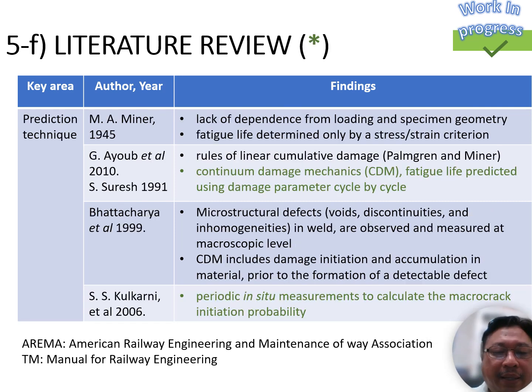On the prediction techniques, the author has extended an additional review on prediction. As per analysis, it shall not lack dependence on loading and specimen geometry. It is suggested by Miner in his literature in 1945, and Ayoub et al. 2010 and Suresh 1991 agree on the application of the rules of linear cumulative damage, which shall extend to continuum damage mechanics. So this model needs to be associated with finite element modeling, which was not included in my previous model.